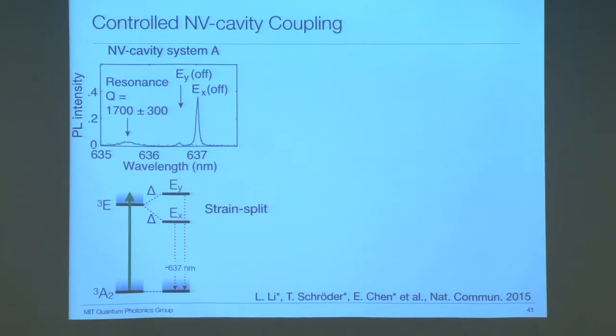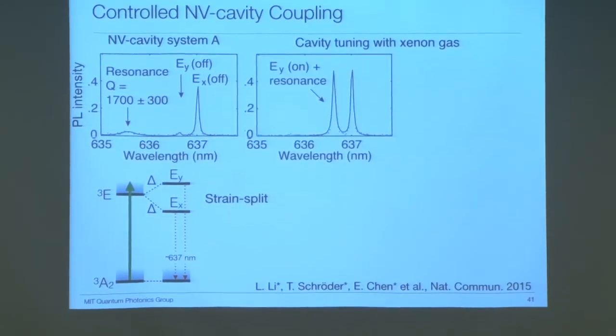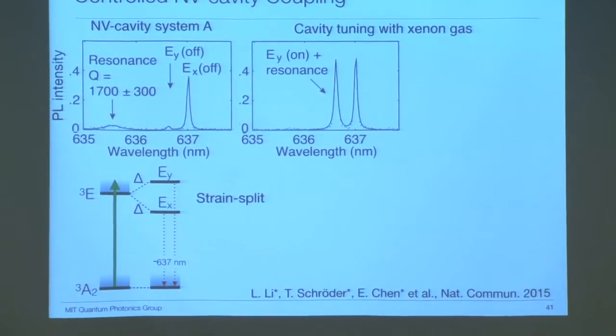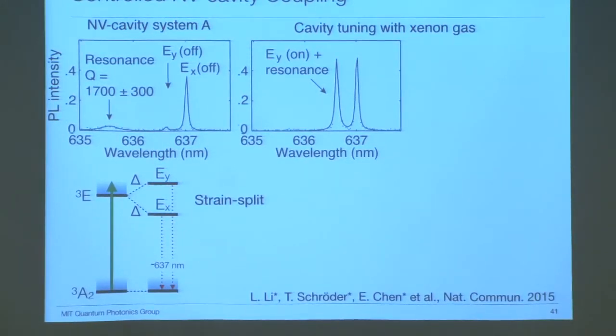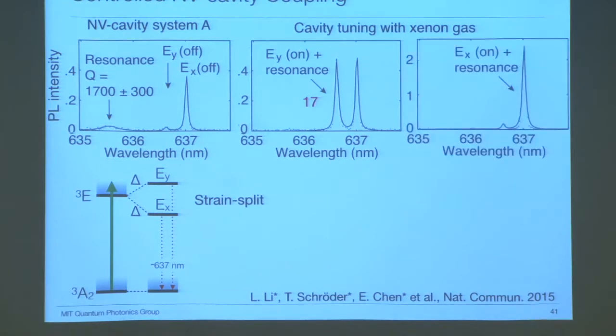And as we inject xenon gas at a cryogenic temperature, this xenon gas would condense on top of the photonic crystal cavity, thus increasing the effective refractive index of the diamond that can be seen by the cavity. The cavity resonance would shift to the red in the spectrum. It first overlaps with the EY transition. And when the EY transition is on resonance, it gives a Purcell factor enhancement of 17. Then it redshifts further and overlaps with the EX transition and enhances the EX ZPL transition as well.